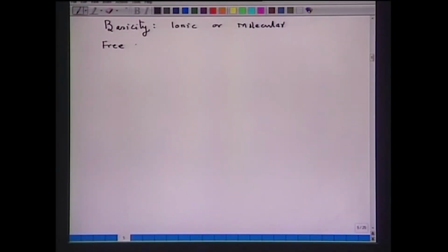When basic oxides are added, oxygen ions will be available, and these oxygen ions break the tetrahedron. So, any free oxygen ions available after satisfying the requirement of all acidic oxides, that is called the index of basicity. That means the presence of free oxygen ions is an index of basicity of a particular slag.